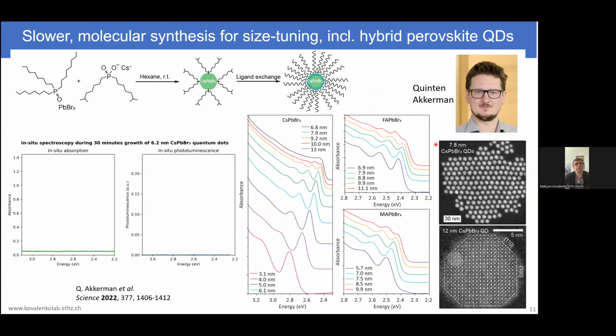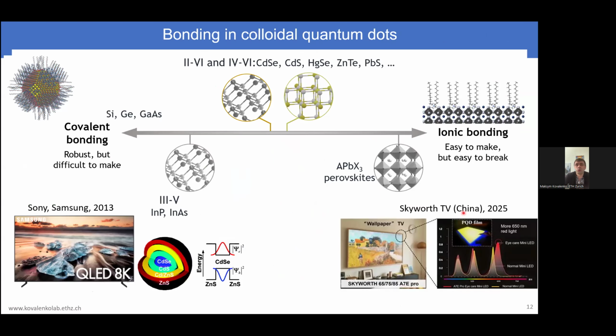Now, a much later advance was that we finally could slow down this formation by a lot. So now you see the synthesis, which is just like two orders of magnitude slower. So you go like 30 minutes to evolve to get to the same size. So you can now precisely control the size, and you see these very sharp molecular-like transitions at very small sizes, very similar to those classical cadmium chalcogenide-based spectra you've seen from Bawendi before. So by now, there is full control over the size and the formation of these dots. They can be spherical, they can be cubic, or other shapes. And since last year, they also have become a commercial product. The first, as a television display.